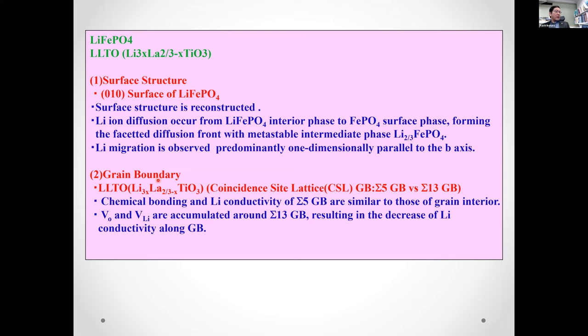For the grain boundary characterization of LLTO, we applied CSL theory to compare the Σ5 and Σ13 grain boundaries. And we found that the chemical bonding and the lithium conductivity of Σ5 are similar to those of the grain interior. And oxygen vacancy and lithium vacancy are accumulated around the Σ13 grain boundary, resulting in a decrease of lithium conductivity around the grain boundary.